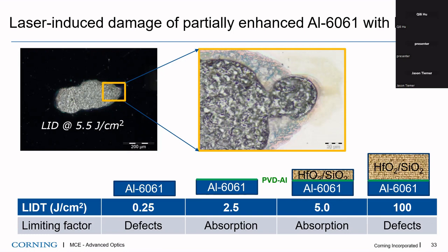And then when we put a dielectric layer, 5 periods there, you can further increase the damage threshold to 5. And then the more you add, the higher the damage threshold. But one condition we need to make sure is that there is no defect. If there is a defect, then the thicker the layer you put, it still forms the nodular defect. So based on that, we collect what the damage limiting factor is at a different stage or different configuration.